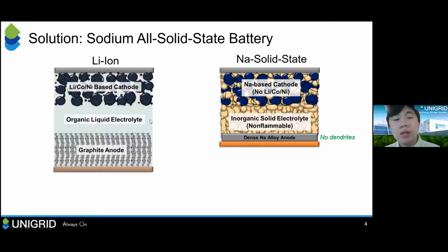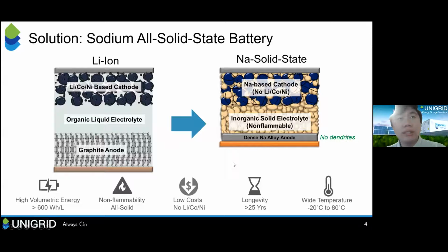Compared to this traditional chemistry, we instead completely eliminate the lithium, cobalt, nickel, and other expensive elements from the cathode in order to keep costs low. We also replace the flammable organic liquid electrolyte with a highly stable solid-state ceramic. So in other words, it is non-flammable at all. Finally, we also replace the carbon-based anode with a very dense, or sometimes we call it dendrite-free, sodium alloy, which allows it to take up much less space. So overall, this gives us the ideal combination of high volumetric energy density, absolute non-flammability, so we dramatically reduce risks, and it is much lower in cost.